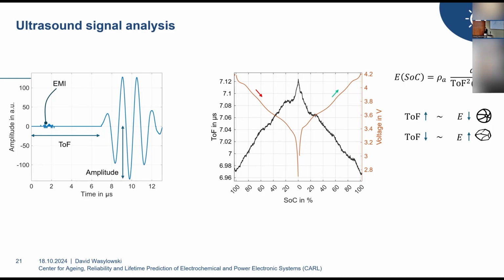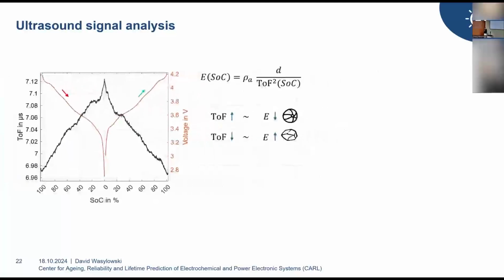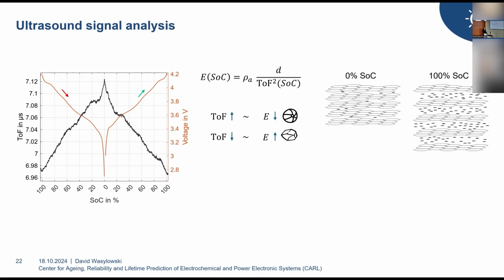And in order to understand why this change is happening, we need to have a look at the material level. And we know from prior studies that most of the mechanical change within the battery is occurring at the anode. So if we now have a look at a fully discharged anode, we have these graphite layers. And if we now charge the anode, the lithium ions would be placed nicely in between them until there is no more room for any additional lithium left. And this is how a fully charged anode would look.